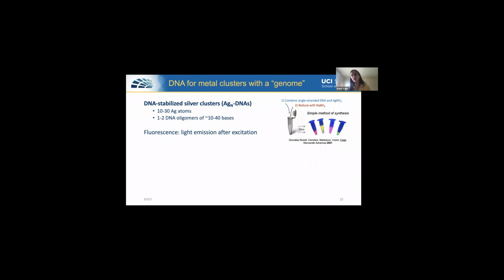And if we've done this properly, after some amount of time, a few hours or a few days, we'll find that our tube is glowing. And that glowing is coming from these DNA stabilized silver clusters. So specifically, the type of glowing is called fluorescence. This is light emission after we excite the cluster with light. In this case, we're using a black light, kind of like you might see at a party or something, in order to excite the fluorescence.